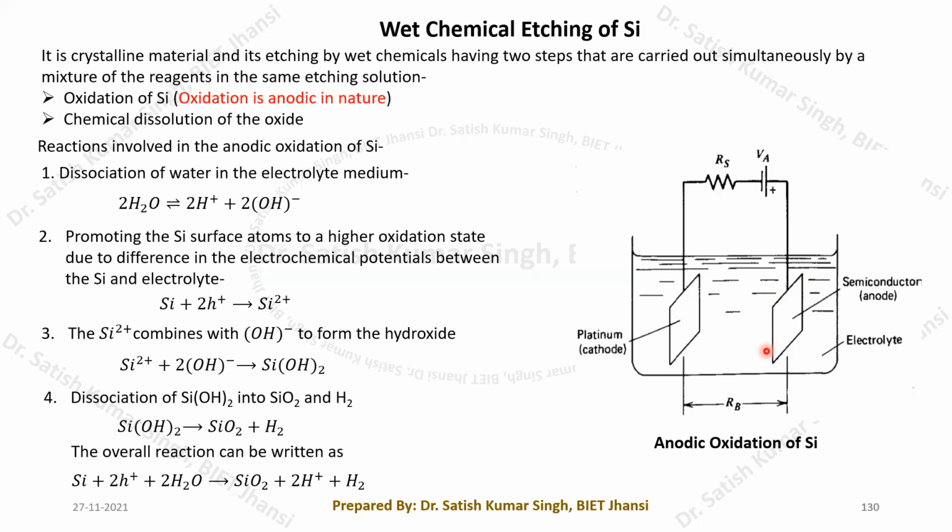You remember that it is very difficult for an n type wafer surface, because at that time the holes are not the majority charge carriers, and generally it has been found that this semiconductor and electrolyte interface forms a depletion region with a barrier corresponding to a Schottky diode.